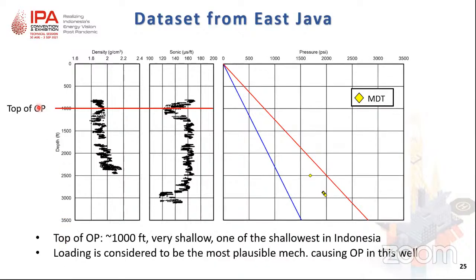The top of overpressure in this well, 1,000 feet, is considered very shallow, and probably, to my knowledge, this is one of the shallowest tops of overpressure in Indonesia. Overpressure in this well is responded by density and sonic log, and down to the TD of this well, 3,000 feet, temperature is not yet sufficient to generate any plausible unloading mechanism, such as clay diagenesis and hydrocarbon maturation. It then can be interpreted that loading is the only cause of overpressure in this well.